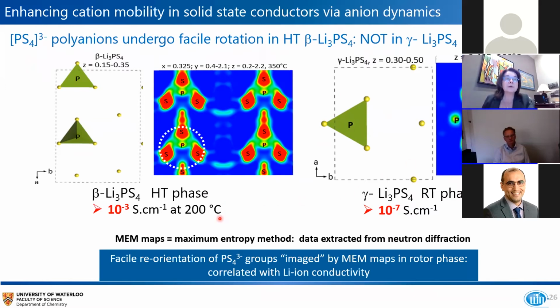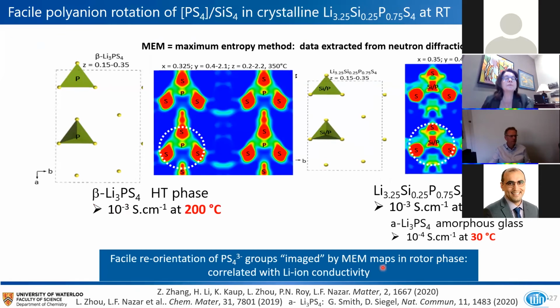Whereas at the same temperature, well, this happens to be at elevated temperature because we had to record at elevated temperature, you can see that the thiophosphate groups are showing rapid reorientation. Now, we don't know how fast this is. We can just see that the sulfur density is smeared out, indicated by these green patches. So this is a direct image of this reorientational motion that is imaged by these maps. And it's correlated with lithium ion conductivity, as I'll explain in a moment.